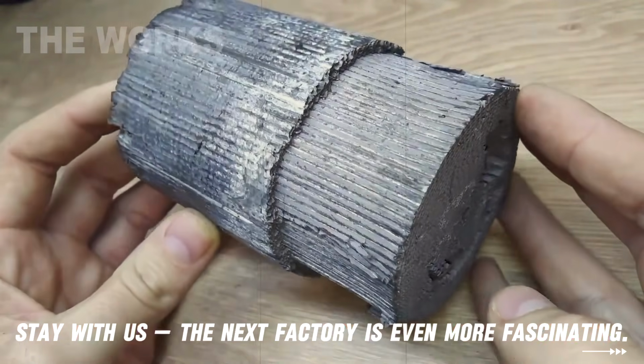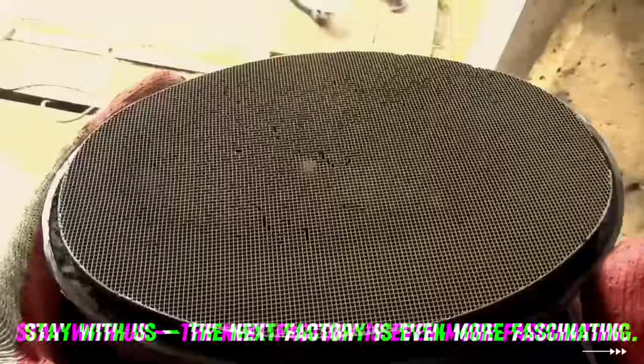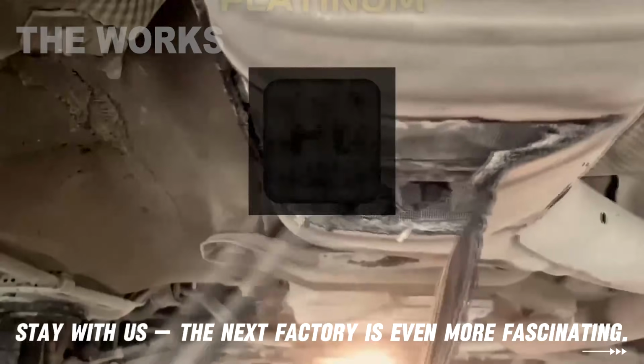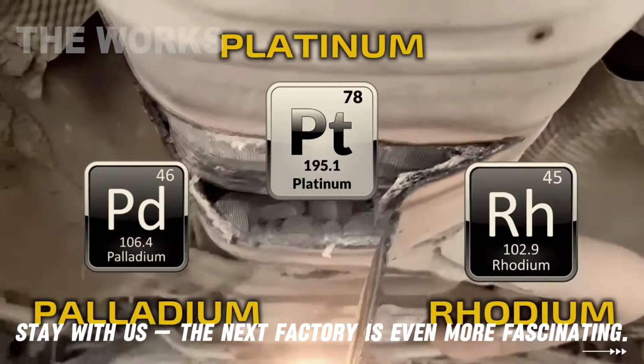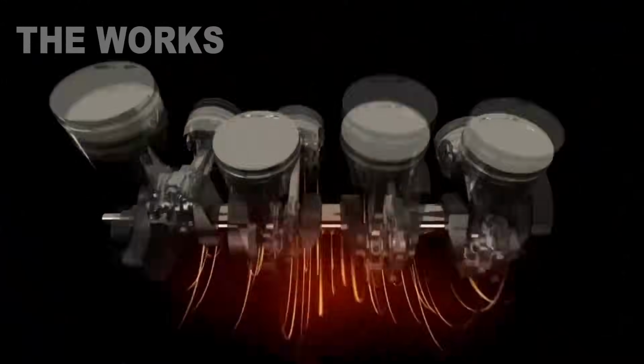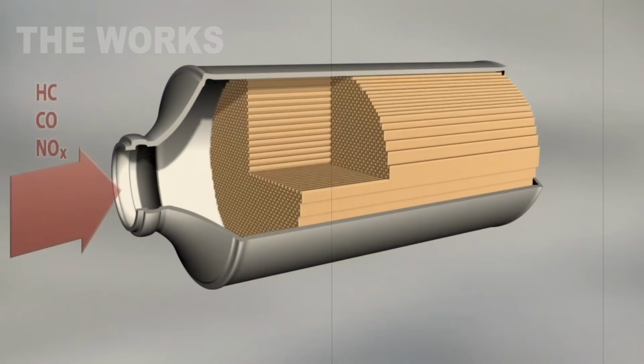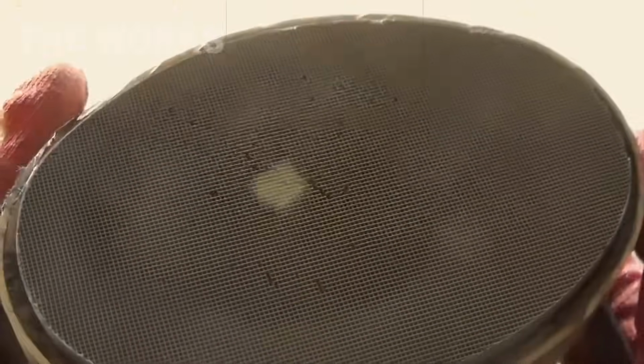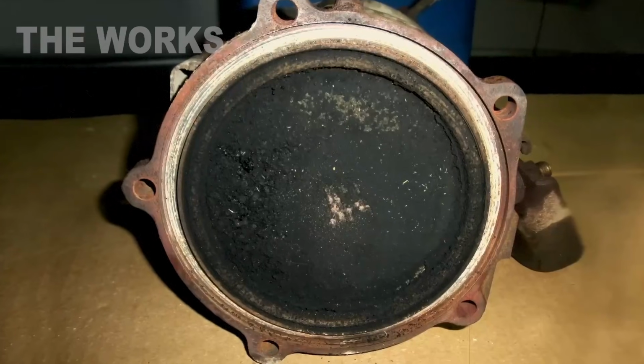Inside a stainless steel casing, a ceramic honeycomb structure coated with an ultra-thin layer of platinum, palladium, and rhodium. Hot exhaust gases pass through the honeycomb. On the surface of the platinum group metals, reactions occur. Carbon monoxide converts to carbon dioxide, nitrogen oxides to harmless nitrogen, hydrocarbons burn off. The converter cuts emissions by 95%. But there's a price. Each converter contains precious metals.